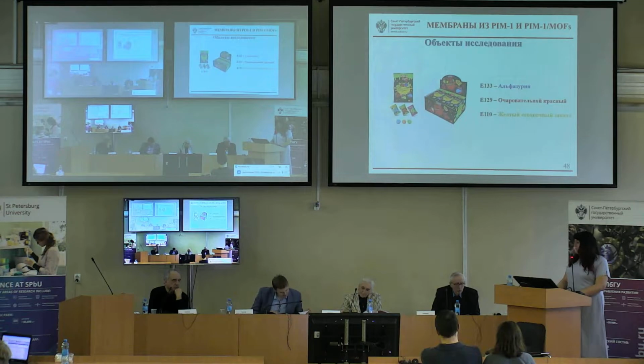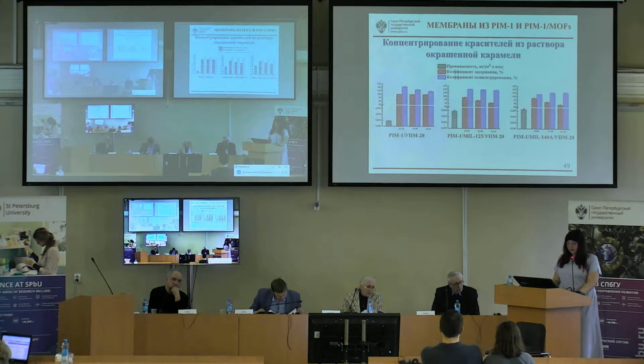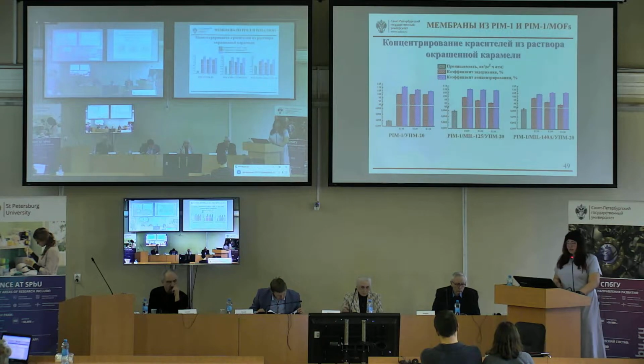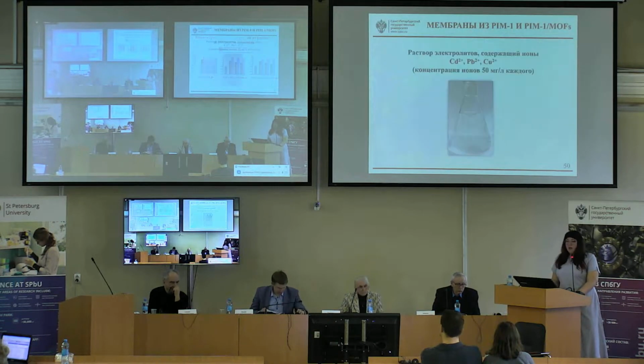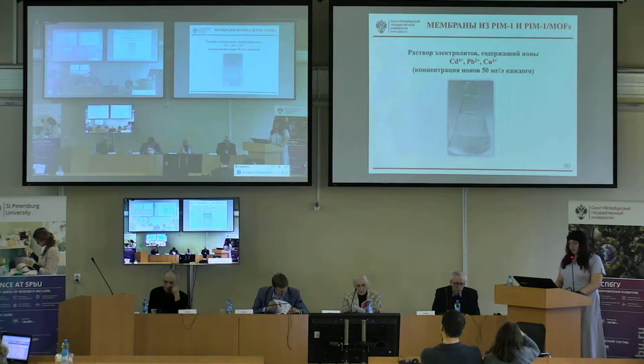but a slight decrease in the values of the retention and concentration coefficients. Next, the concentration of 3 food colors from a real object, dissolved caramel, was carried out. The graph shows the values of permeability, retention factor, and concentration factor for a caramel solution containing three dyes. It was found that the modification of MIL-125 and MIL-140A membranes leads to an increase in permeability, but a slight decrease in the values of retention and concentration coefficients, as in the case of nanofiltration of a model mixture containing 2 dyes.